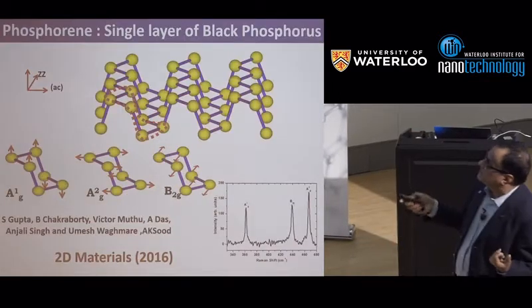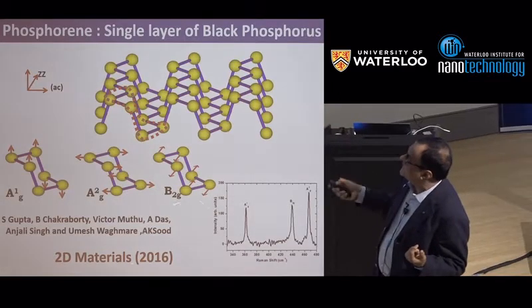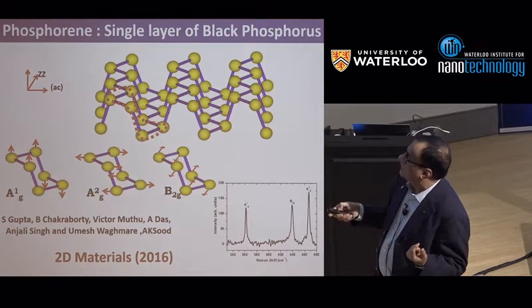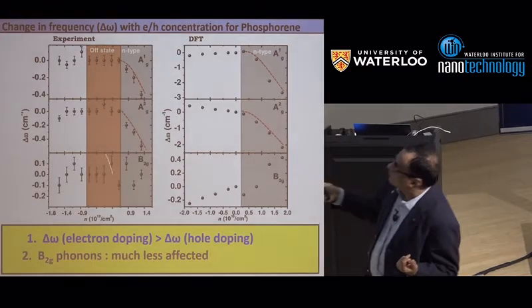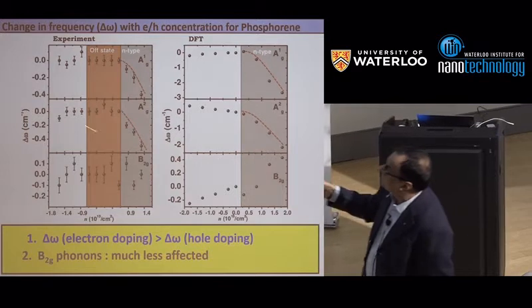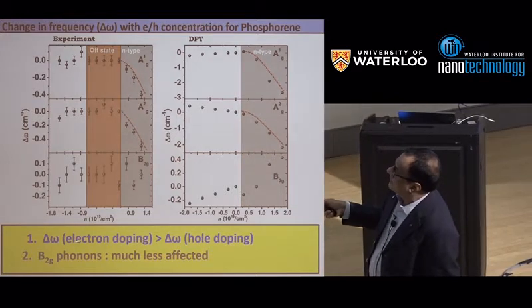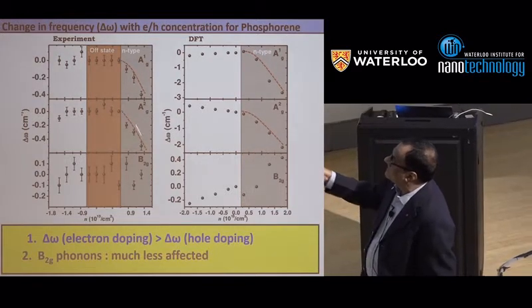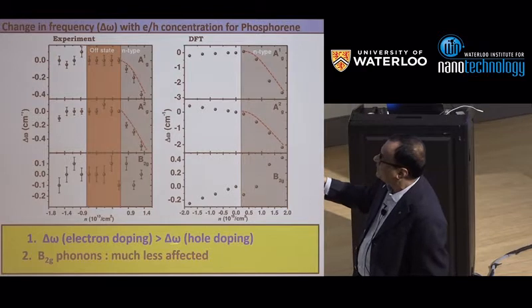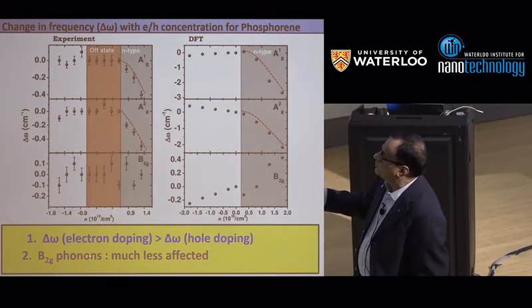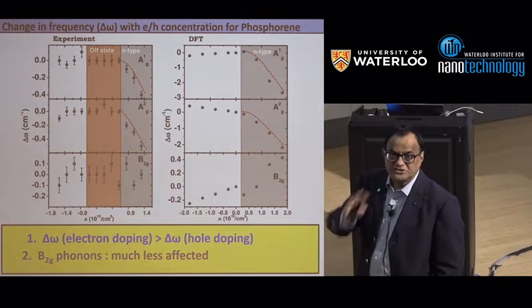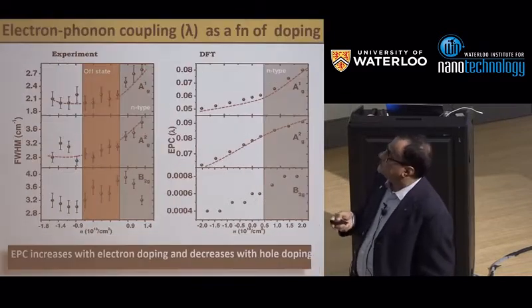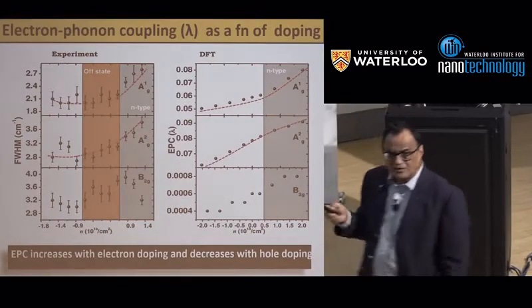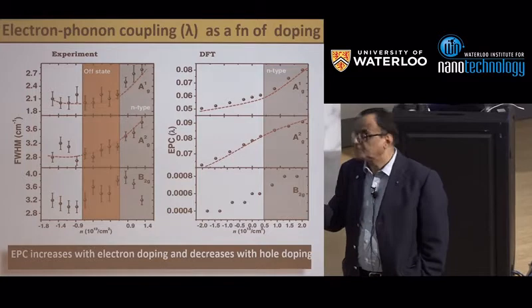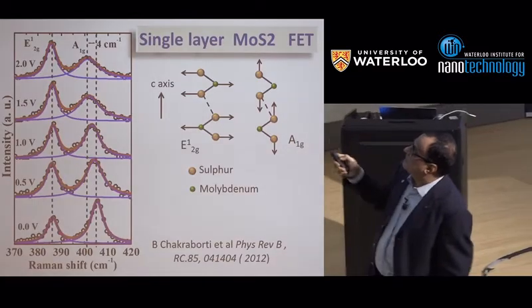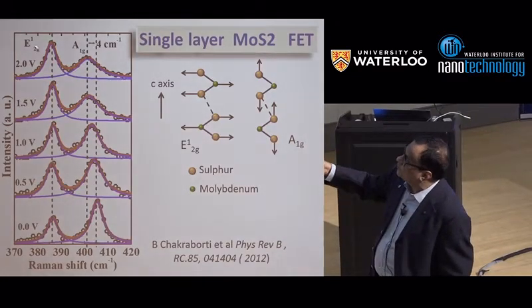So we did this for single-layer black phosphorus more recently, and I don't want you to go into the numbers, but here what happens is that the electron doping effects are much larger than the hole doping effects, and the B2G phonons are not affected, only the A1G phonons are affected. So the symmetry of the phonon is important, and we can find out which phonons are coupled. For example, in MoS2, you have two phonons here.